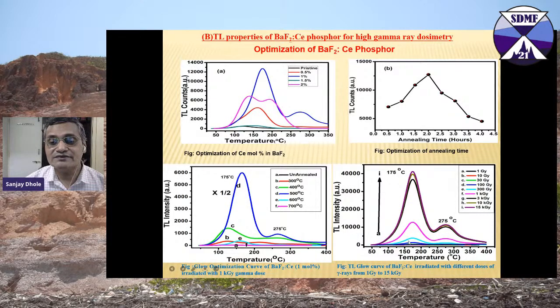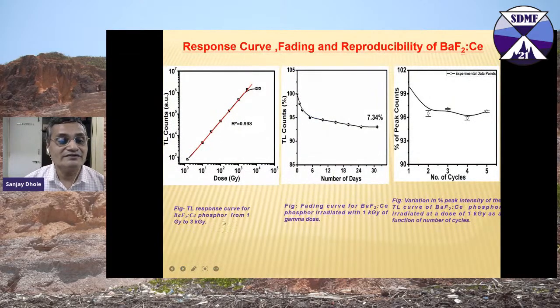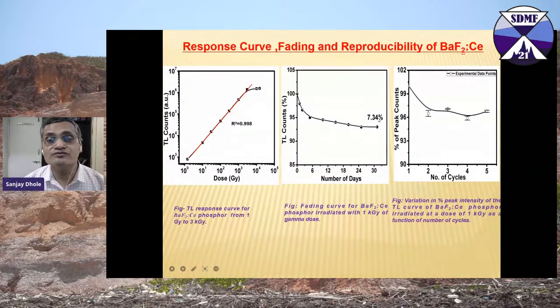You can irradiate from 1 gray to 15 kilogray, and as you go on increasing the dose of the gamma radiation, the intensity of this glow curve increases. So again, it can be used for 1 gray to 3 kilogray. All of them can be used almost for 1 gray to 3 kilogray, and you have a fading of 7.34%, and again the reproducibility can be obtained very nicely.